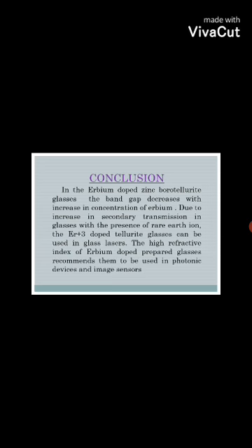From our project, we can conclude that the band gap decreases with the increase in the concentration of erbium ions. Now, we have seen from the graph that transmission is increased with the presence of rare earth ions, that is erbium ions. So, the erbium doped tellurite glasses can be used in glass lasers, and because of the high refractive index of the glasses, they can be used in photonic devices and image sensors.